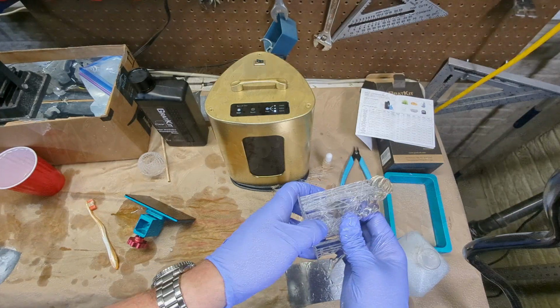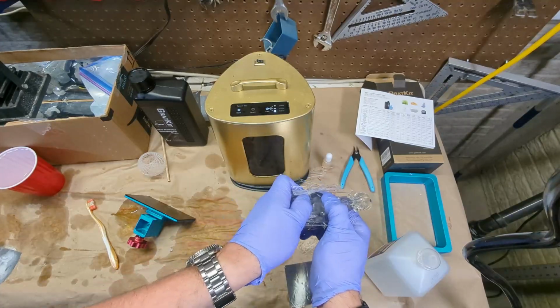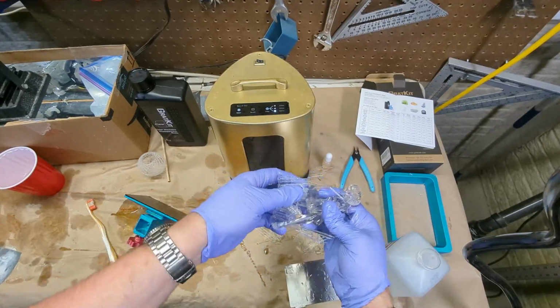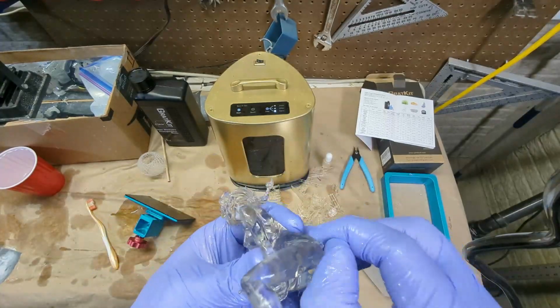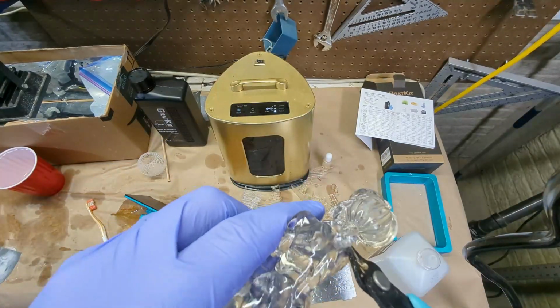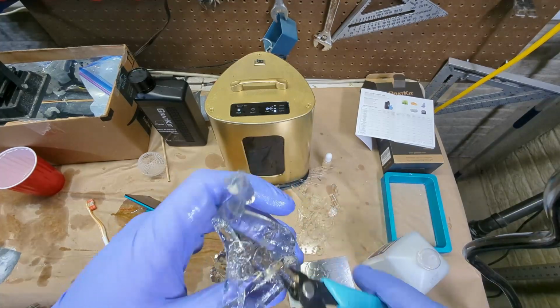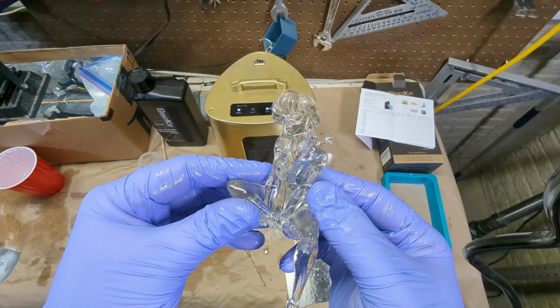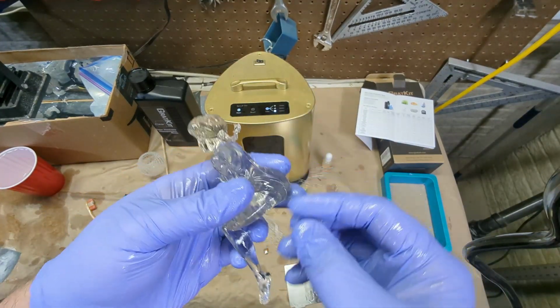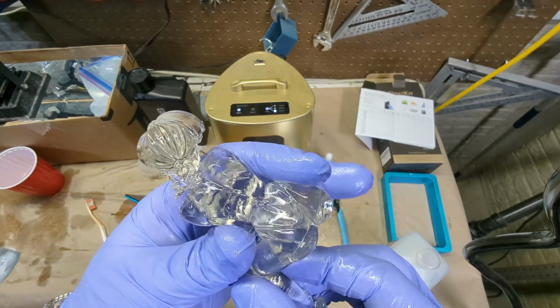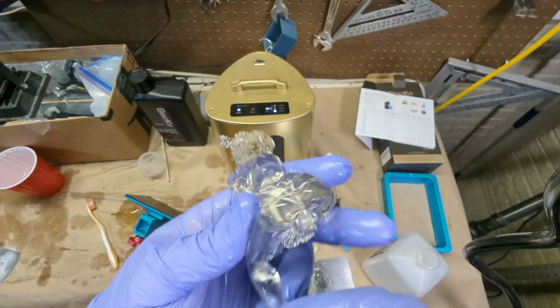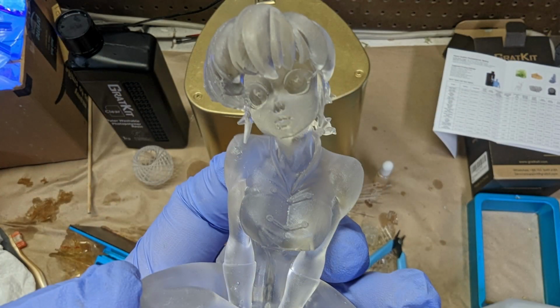Now back to the figures, I was able to get them to print while adhering to supports by increasing the cure time from the 6 seconds I was using to 12 seconds. One downside to increasing the time is that the supports were a pain to take off and there was additional cleaning that had to happen afterwards. Now you'll see here, there's a little clouding to be expected, but overall the print came out really well. It's still fairly clear and it looks well with a lot of detail in it.